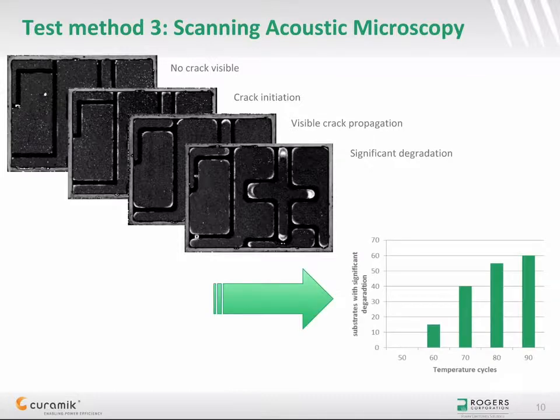However, there is no detailed and accurate definition of when a degradation in the substrate can be classified as significant. Basically, degradation in the substrate should not impact the heat dissipation from the chips, but this depends on the position of the chips relative to the degradation. As a consequence, this visual assessment leaves much room for interpretation.